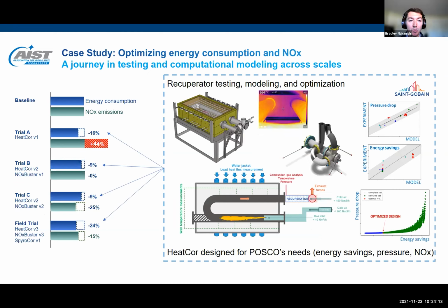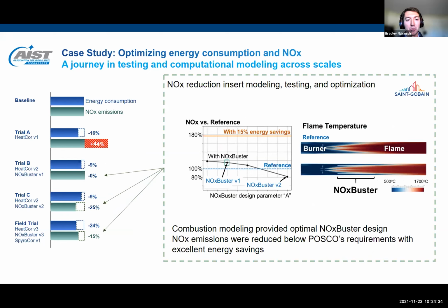Notice in trial A, with heat core version 1, without a NOx buster, 16% energy savings are obtained, while NOx increases by 44%. This is a direct result of the higher combustion air preheating with heat core. To combat higher NOx, NOx buster, a ceramic insert, may be positioned downstream from the burner in the flame, reducing both peak temperatures and NOx, as the figures on the right illustrate. After just a few iterations of testing at RIST with modeling input from Saint-Gobain, we created a NOx buster that reduces NOx below POSCO's targets while providing significant energy savings.